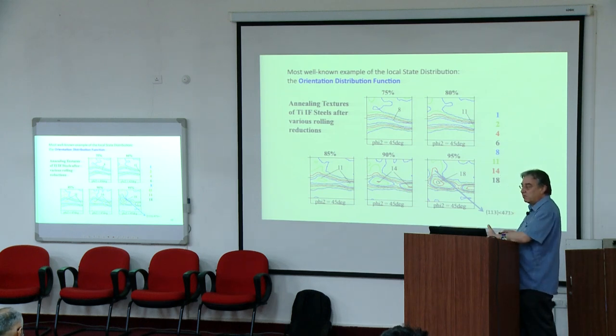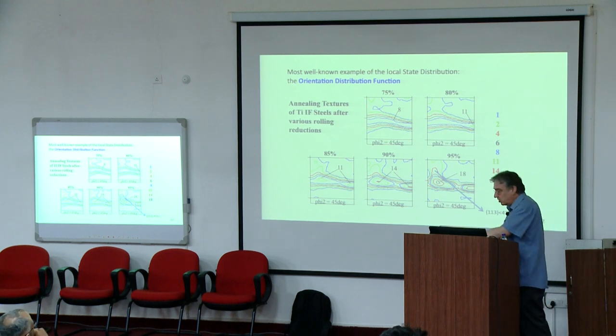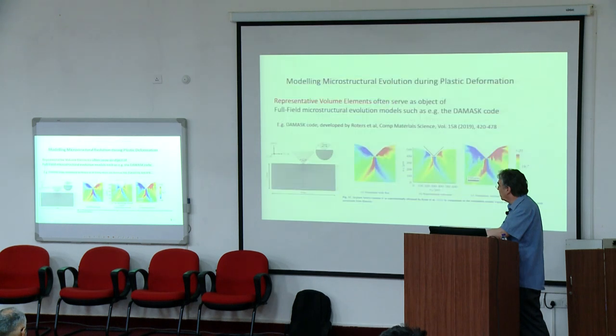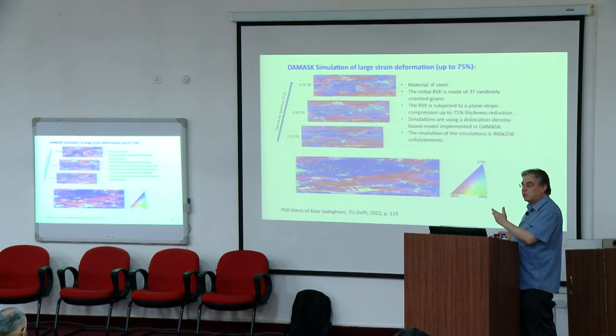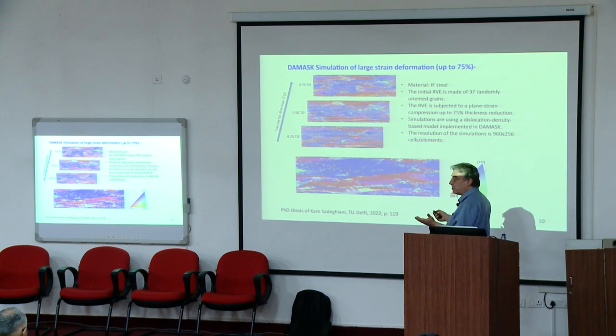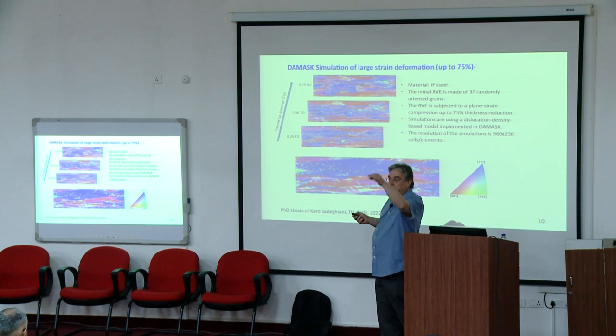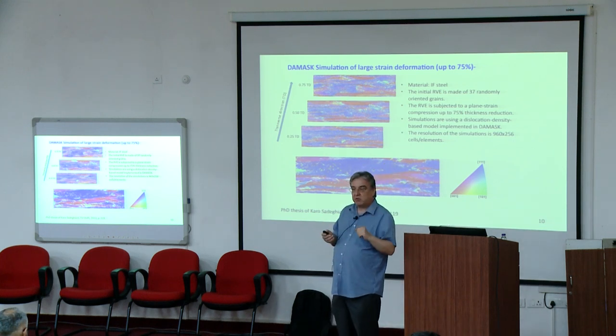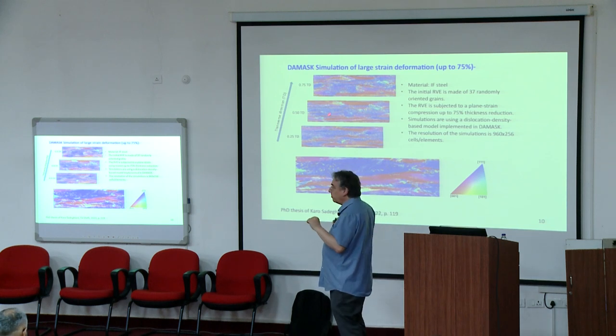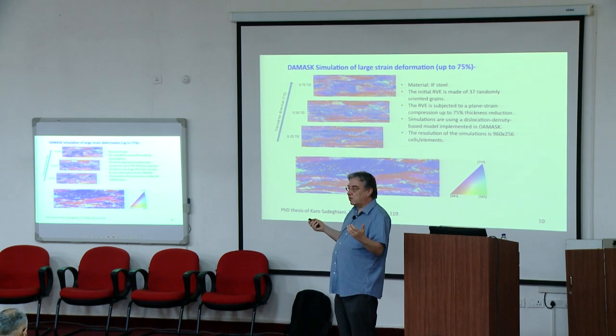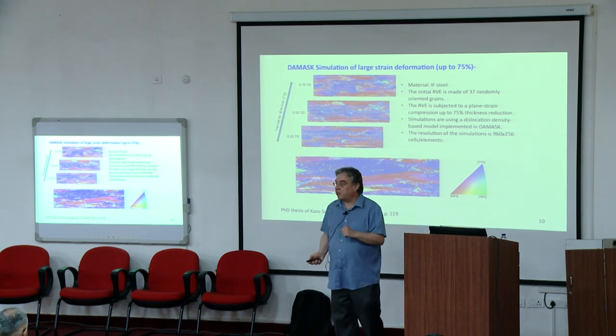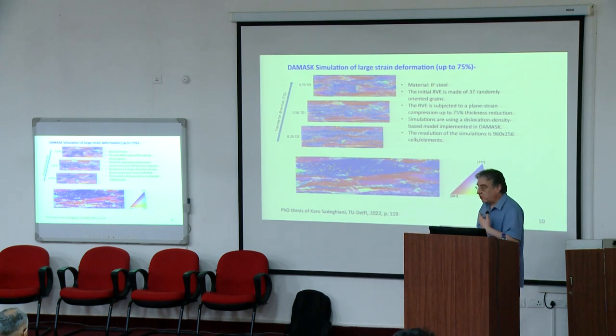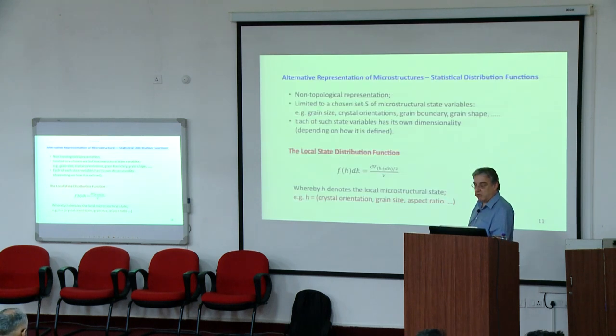Of course, we don't have that much information. We only have the information of the texture. In this drawing, this corresponds to the color of the grains. Color of the grains represents here their crystal orientation. So with a statistical distribution method, you forget about the local topological position of each grain and their neighborhood and so on. You don't care about it. But you just, for example, we have considered the marginal distribution of the crystal orientation, which would be then the color distribution compared to this. So it's, of course, less powerful from the perspective of information that you can model, but it's much more powerful from the time and the cost of the simulation.